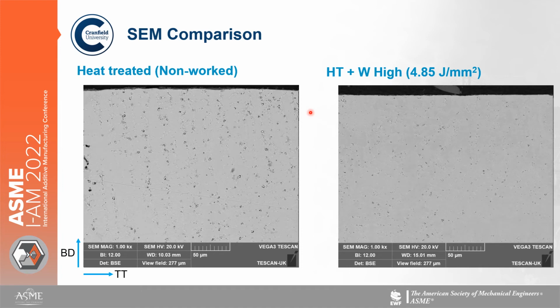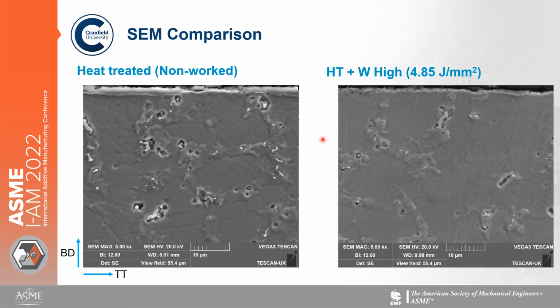And if we switch to backscatter, you can start to see some of these precipitates, brightly coloured precipitates and also darker coloured ones. They're both very similar in both of the samples, which suggests that there isn't a great deal of difference between them. So again, even further zoomed in at 5000 times now, we can see there isn't a great deal of difference between the formed precipitates in both of the samples.